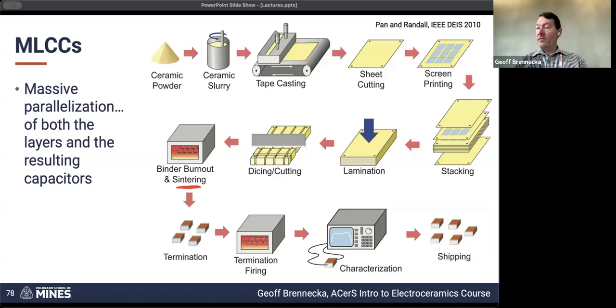And in each case, the ceramic dielectric layer started with roughly 50% solid powder and 50% binder. And the metal layer also started with something like 50% by volume metallic particles in some sort of a binder system. These are very different materials, and we want them to all sinter and densify at roughly the same temperature and time. They have to do this together. And we've already stacked up 5, 10, 1,000 layers of these, and they all have to sinter together, because if they're not sintering together cohesively, then for one, we might end up with stresses that make everything fall apart. For another, we might end up with cracking. And cracks inside of this capacitor are going to be weak points whenever we apply an electric field later on, and it's not going to function as a capacitor.